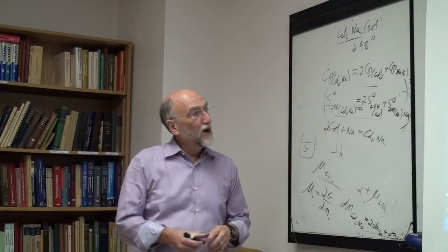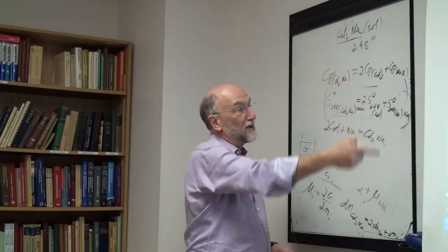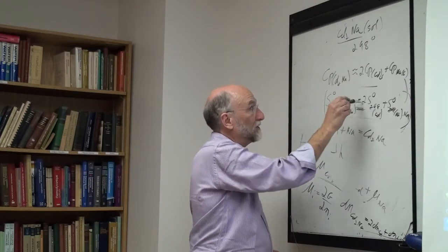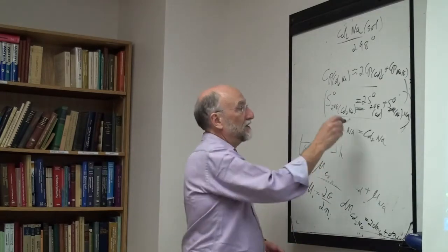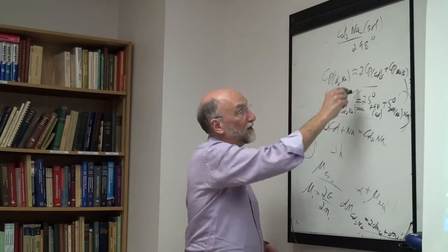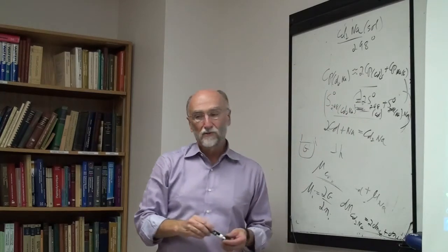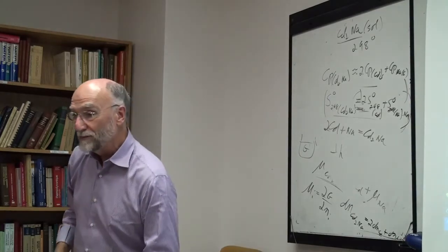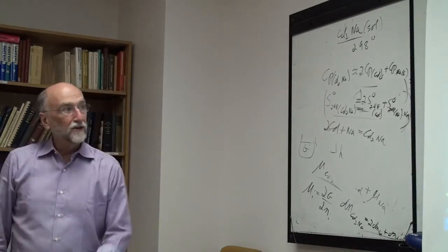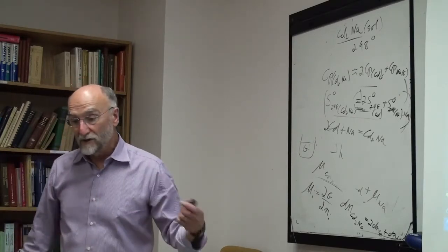So in the papers we write, in this particular example, you'd probably have to assume that was 0, but in other cases, if you had the heat of formation from other measurements at 298, then from these diagrams I could have backed out the entropy. And if I found that the entropy change here deviated more than, say, 10 joules per gram atom from 0, then I would start to question what I was doing. So you always look at your results.